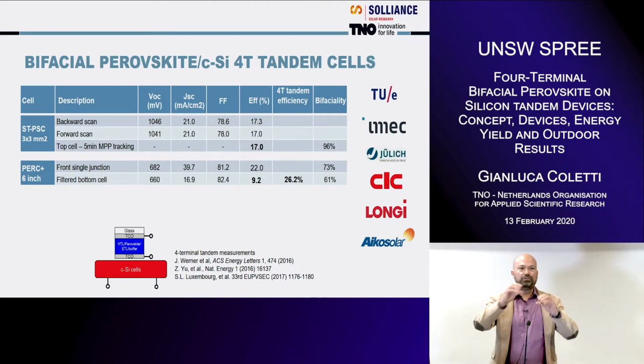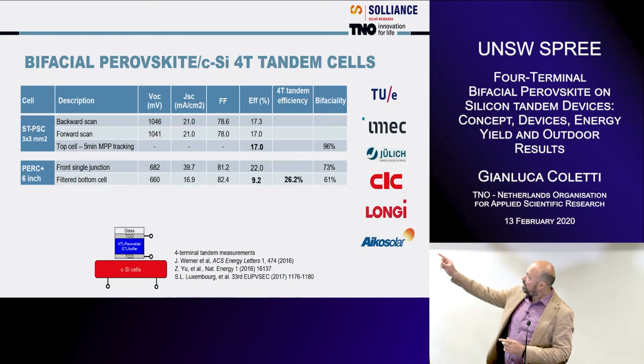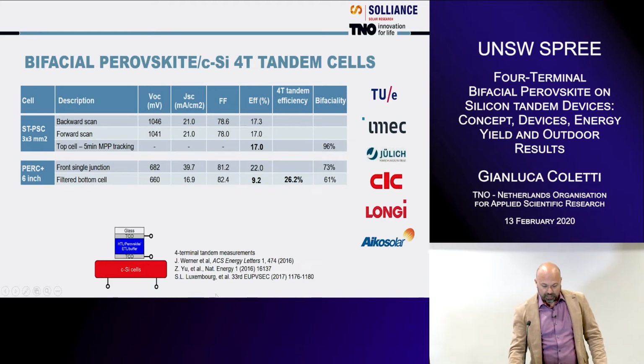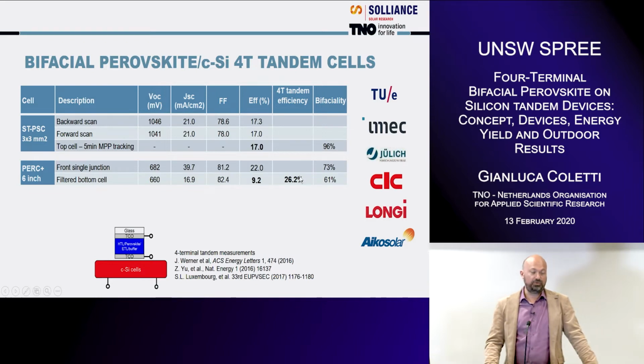Now, when you put this device under the perovskite, part of the light is absorbed by the perovskite, part is transmitted, the near infrared. So the efficiency of the bottom device became 9.2%. Now 9.2%, I think you can see here, added to 17 makes 26.2%. Now this is already something very interesting. You start with a device that is 22% and you can make something in tandem at 26.2%. This is without any bifaciality yet.